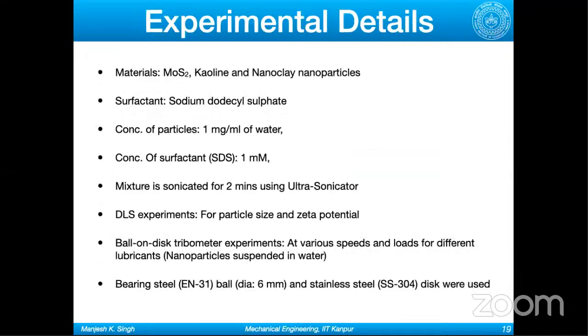In the experiments, I tried different nanoparticles: MoS2, kaolin or nanoclay nanoparticles. The surfactant which I used was sodium dodecyl sulfate, more commonly known as SDS. These are the details of the concentration of particles and the surfactant which was used. To prepare the mixture, we sonicated it for 2 minutes using an ultrasonicator. I didn't mix all the particles together: just one particle plus water, and in one case one particle plus water plus the surfactant. Then we ultrasonicated for two minutes.